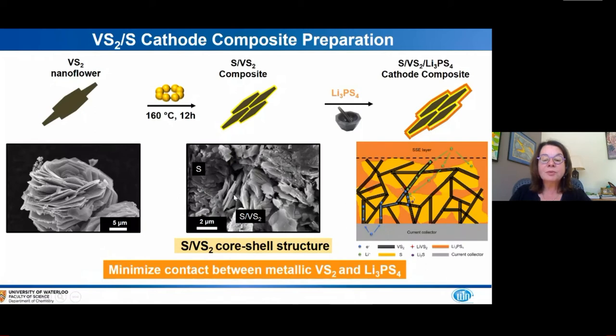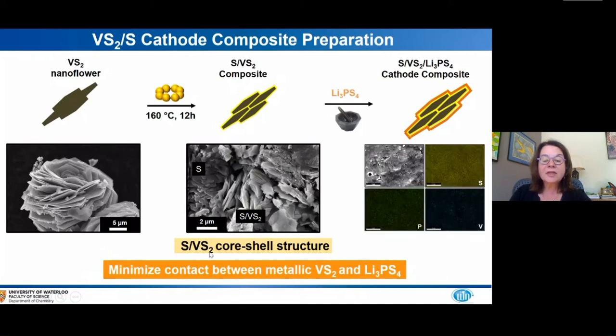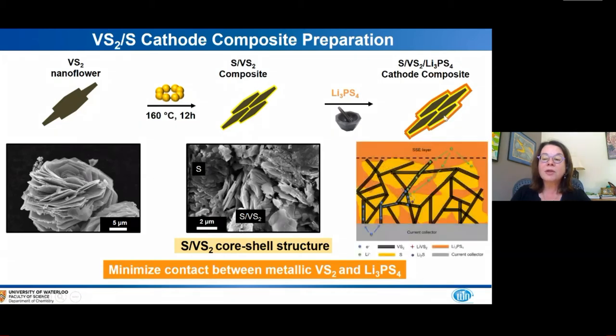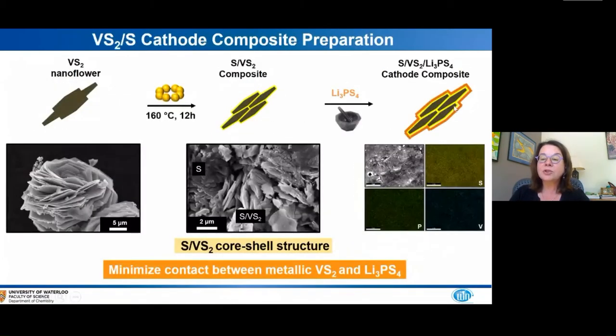Critical here is that we form a sulfur-VS2 core shell structure. The metallic VS2 is completely coated by the sulfur, and the lithium thiophosphate, Li3PS4, incorporates on the outside of the sulfur, so it's not in direct contact with the VS2 metallic sheaths that perform the wiring for the system. Of course there have to be little gaps in between. This isn't exactly a perfect diagram, but this is the concept of this core shell structure.